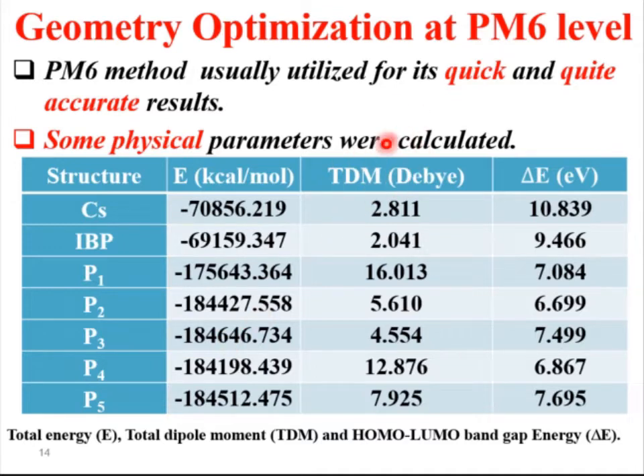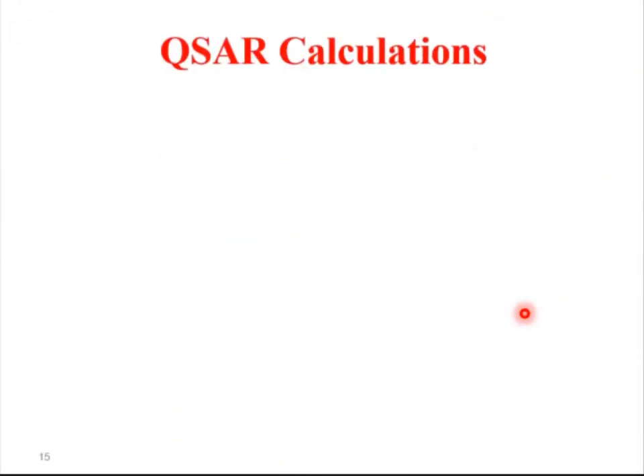Total dipole moment, which is a strong indicator for structure's reactivity, and it's obvious that interacting chitosan silica with ibuprofen results in highly reactive structures, especially the first and fourth probabilities, representing the interaction of chitosan with ibuprofen through its amine group, either through chemical interaction or physical interaction. Then HOMO-LUMO band gap energy, referring to chemical structure and electrical conductivity, and interacting chitosan silica with ibuprofen increases electrical conductivity of the resulting structures. Then some QSAR calculations are considered as following.